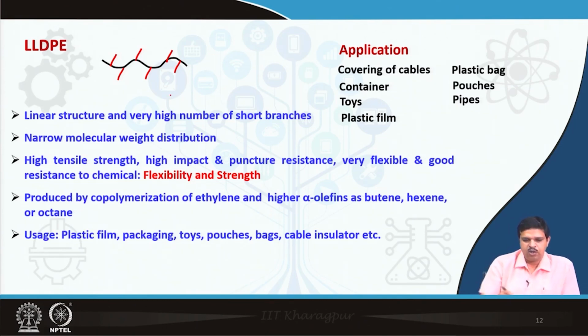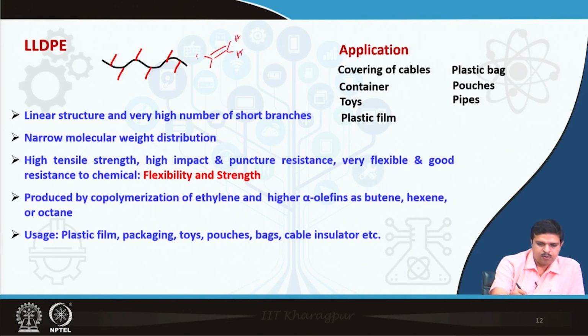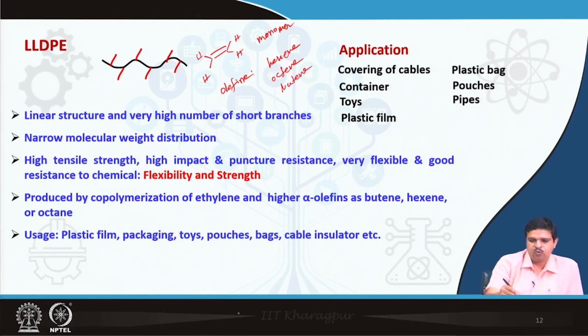And obviously the synthesis protocol is different from the others. Here what we normally do is use ethylene, that is your main monomer, and we use another olefin, for example hexene, octene or butene sometimes, and we do the copolymerization basically with any of these. So, sometimes we call this alpha olefin copolymerization.